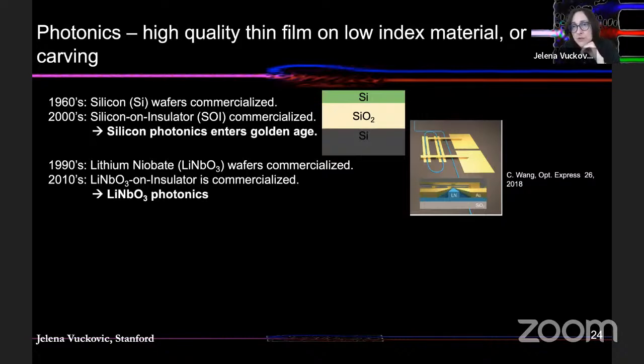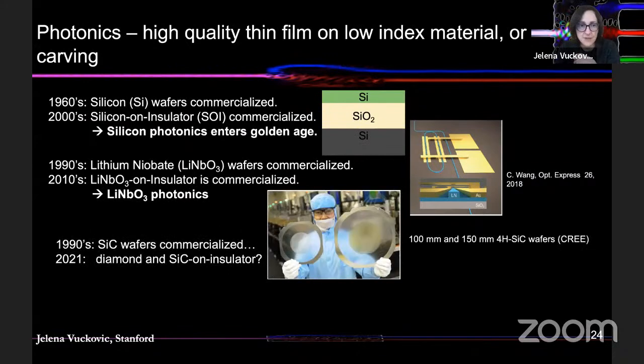But again, part of the reason why this platform has become even more interesting is because there are these thin films that are commercially available, and people can get the wafer and design structures and fabricate devices. But for diamond and silicon carbide that we're talking about here for quantum optics, we don't really have thin film on insulator that you can get commercially. You can get 6-inch wafers of silicon carbide, or you can get a few millimeter chips of bulk diamond, but then you have to figure out how to make photonics. And that's not a trivial process.